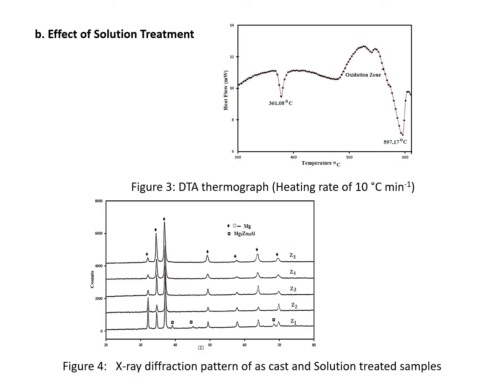Effect of solution treatment. The DTA thermograph of ZA85 alloy is presented in figure 3. It has been observed from the figure that the endothermic peak at 361.08 degrees Celsius for the as-cast samples corresponds to the ternary eutectic dissolution temperature.